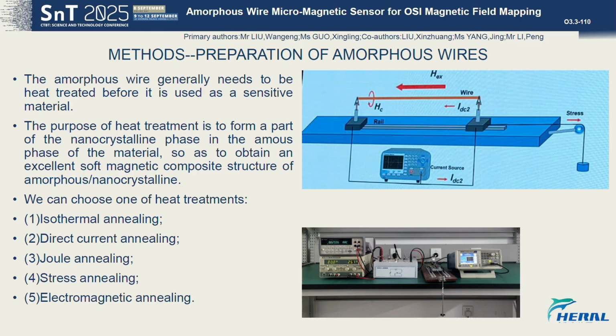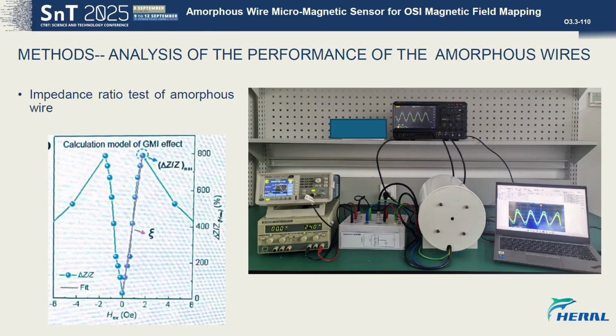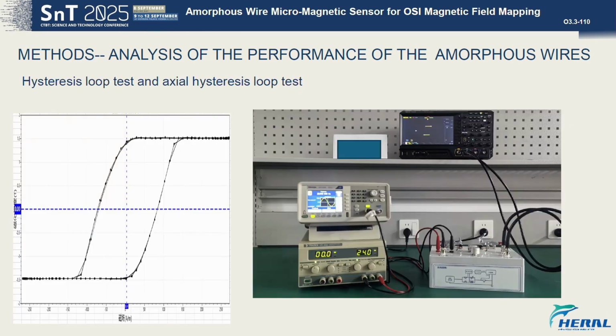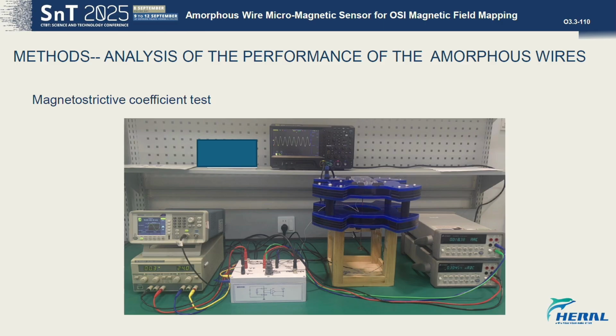The purpose of heat treatment is to form a part of the nanocrystalline phase in the amorphous phase of the material so as to obtain an excellent soft magnetic composite structure of amorphous or nanocrystalline. We can choose one of the heat treatments such as direct current annealing, Joule annealing, stress annealing, and electromagnetic annealing. After heat treatment, we must analyze the performance of the amorphous wires, such as impedance ratio test of amorphous wire, hysteresis loop test, axial hysteresis loop test, and magnetostrictive coefficient test.